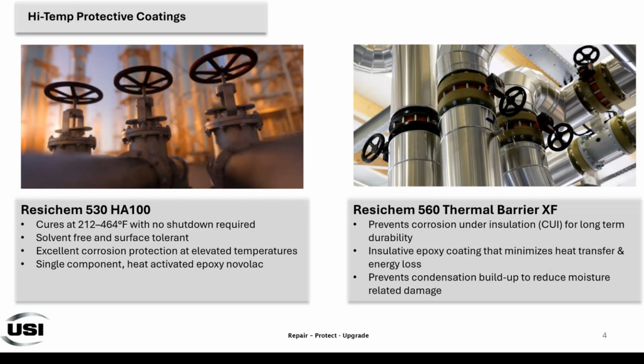Another product, if you have a pipe that you can't cool down to apply the coating, is a Resichem 530 HA100. It cures at 212 degrees F all the way up to 464 degrees F. So there's no shutdown required of the temperature of the coating, and it is excellent for corrosion protection at elevated temperatures and is a single component heat activated epoxy Novolac system. So that one would actually need heat to cure.